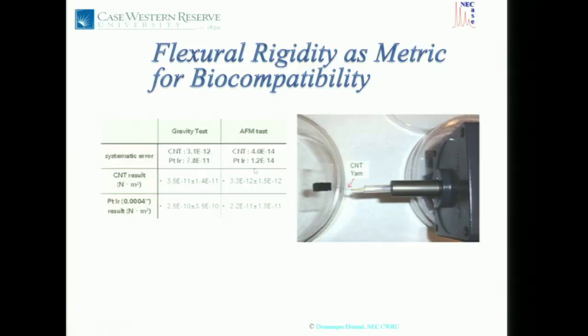Meanwhile, though, we did measure, that's the work of Yang Zhang, who did his master's measuring the flexural rigidity of these tiny structures, extremely flexible. And that was a challenge. We spent a lot of time. We eventually found that we could use atomic force microscopes, which have a picoforce measurement system. You apply force on the yarn, and you measure displacement. From these measurements, you can actually extract the flexural rigidity of these tiny wires. And you find it's in the range of 10 to the minus 12 or 11. So that's quite flexible. So how do you put them in?